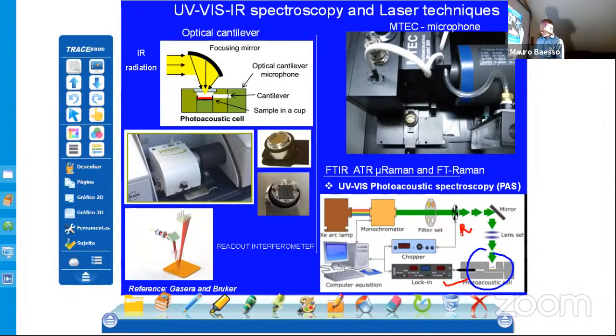One important point in this technique is that when you change the modulation frequency of your chopper, you can get different depth penetration of your sample, and then you can do some kind of depth profile imaging for your material. And also, this is for when you use UV spectroscopy. This is a conventional one. You use a xenon lamp and a monochromator, and then you have a measurement wavelength by wavelength.